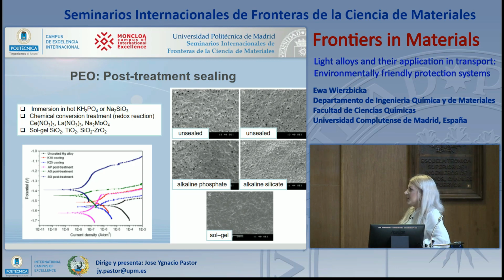Of course, because PEO is also a porous structure, we can use post-treatment sealing. So by application of some solutions or even chemical conversion treatments, we can reduce the porosity of the coatings, which very successfully reduces the corrosion current or moves the corrosion potential to higher values.